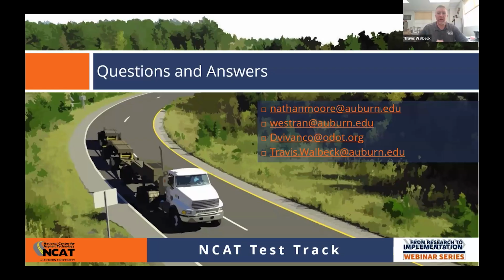Randy, you had the slides that showed very much that the oxidation occurs in the top layer of the asphalt, and it ages less as you get deeper down in there. So one person had a question, Jonathan did, about how does that loose mix critical aging really compare if the majority of our mix is not aging as much as that surface? Yeah, it's a real gradient. And so we're not simulating that gradient, but if we're just talking about the surface mix, the only way to create that accelerated aging throughout that mix is through loose mix aging. So it's again a simplification.